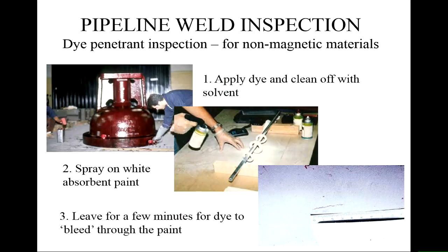A sort of variant on this, which is better for non-magnetic materials but can also be used on magnetic materials as well, is dye penetrant inspection. So dye penetrant relies on the fact that if you've got a crack or a crevice, a low viscosity liquid will be drawn into those cracks and crevices by capillary attraction. So if you coat the whole surface of your component, you can see there with the red dye, wash that off and then spray it with a chalk-based absorbent paint, that paint will sit on top of this crack. The crack's got the dye in and the paint is absorbent, and it will suck some of that dye back out of the crack and leave a red mark on the surface.